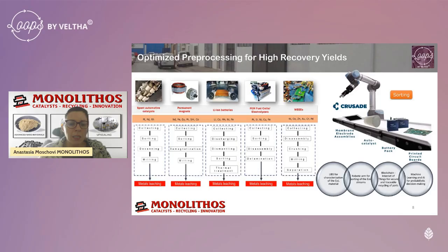What we have concluded so far is that in the leaching process using hydrometallurgy, the highest quantity of the metals is extracted, if not the total amount of the metals. What defines the recovery rate in these steps is the pre-treatment process that takes place before the leaching, before applying hydrometallurgy: the downsizing of the materials, a reduction of the components if needed, reduction of the metals, thermal treatment or mechanical treatment. This is very critical for the recovery rate of the metals.